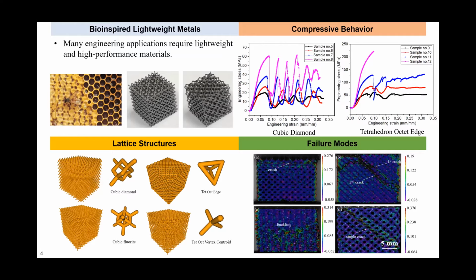So the goal is to customize or tailor or tune the mechanical behavior of these 3D printed lattice structures. Here I only show two stress strain curves of two 3D printed lattice structures with cubic diamond and tetrahedral octet edge unit cell structures. And you can see here, these two lattice structures exhibit very different mechanical behavior based on the stress strain curves.